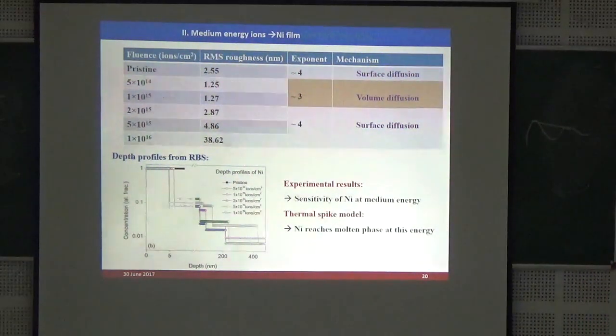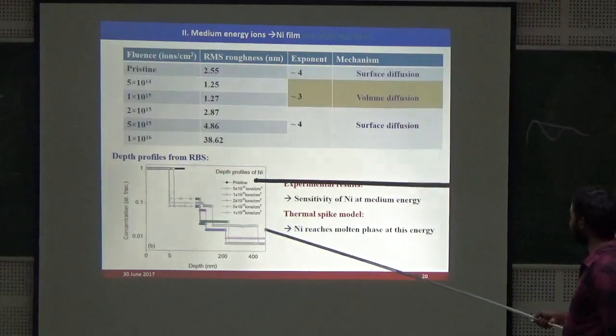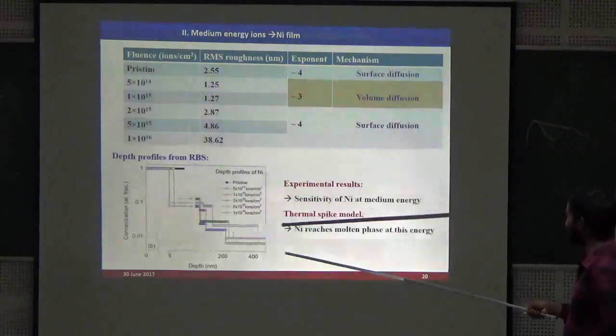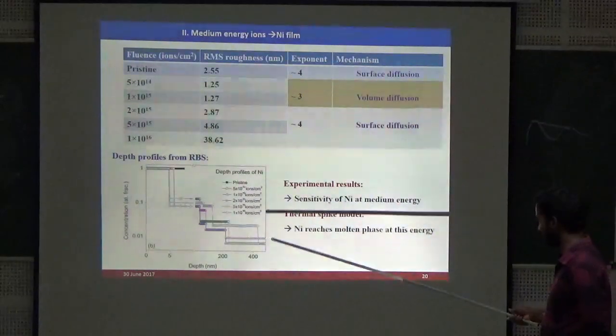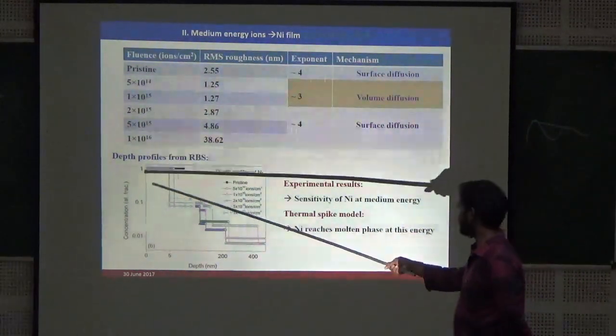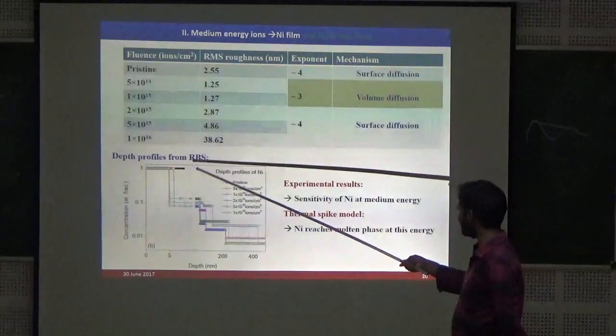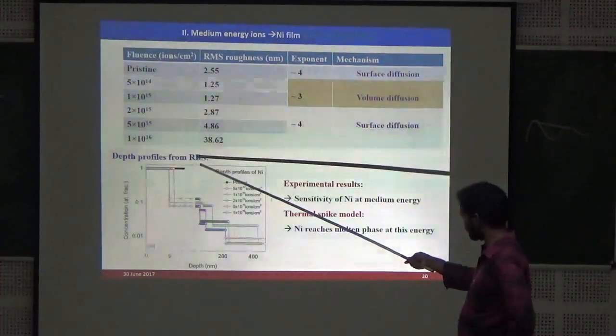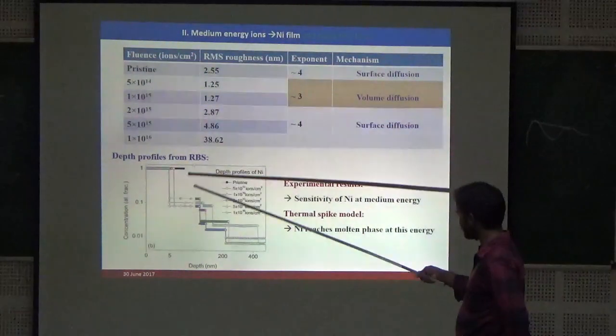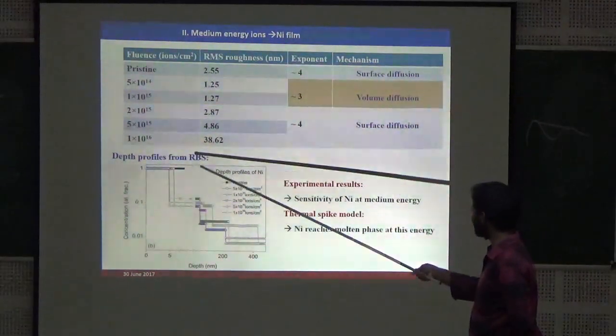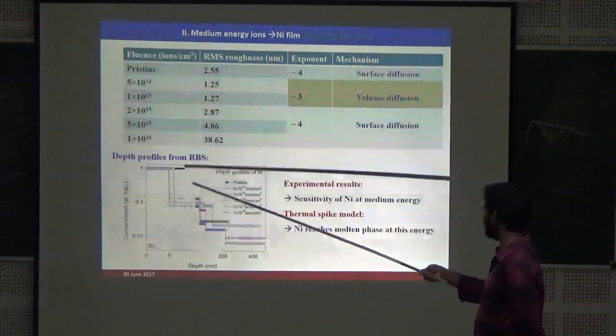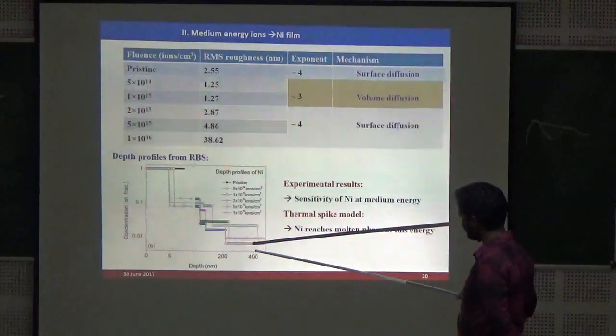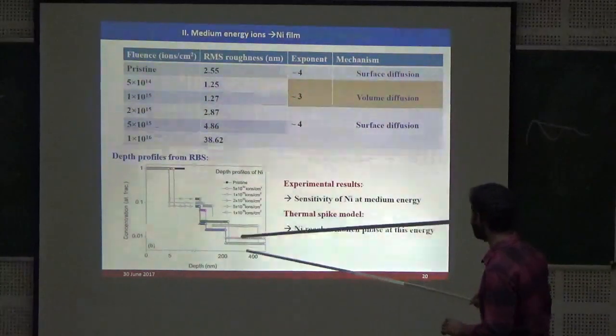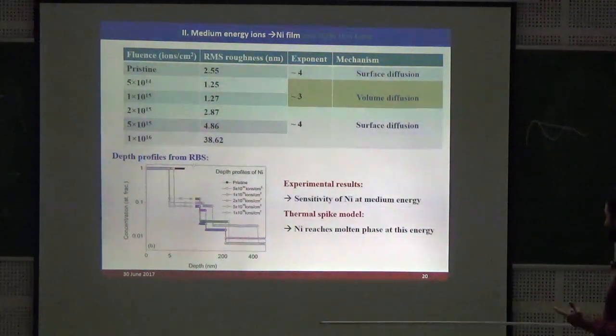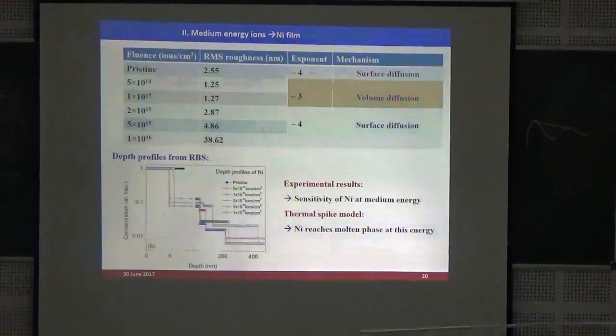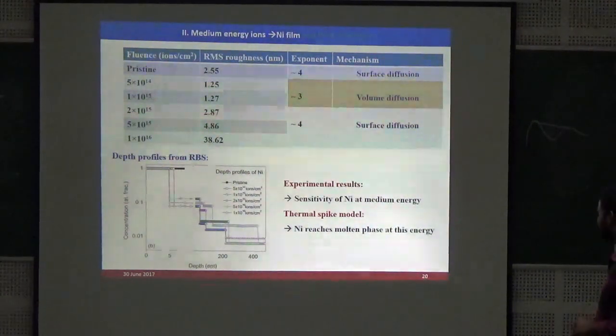So we have done RBS measurements on all these samples, and we have extracted depth profiles as a function of fluence. Here you can see the black color one is for the pristine. It is there from the surface to almost 7 nanometers, and then it is not there. After ion irradiation, nickel is penetrating much deeper into the substrate. That means nickel is not insensitive at this energy level. Even the thermal spike model also suggests that Ni reaches molten phase.